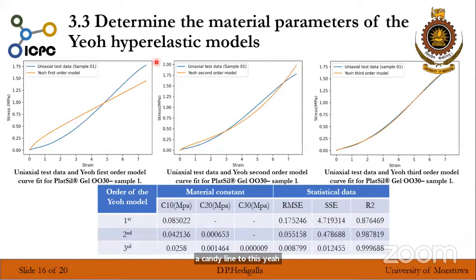And to determine the material parameters of the hyperelastic model that we can use to determine the strain behavior of the silicone material, here you can see the Yeoh first, second, and third order models fit with the uniaxial test data. Here, graphically and the statistical data conclude that the Yeoh third order model is suitable for determining the strain behavior of the silicone material.